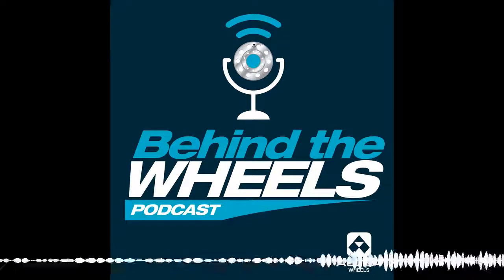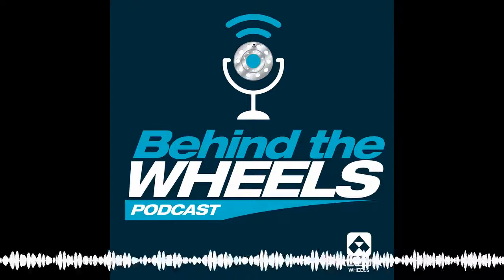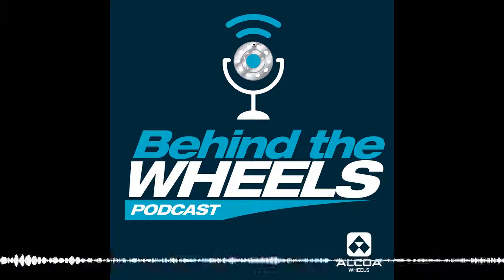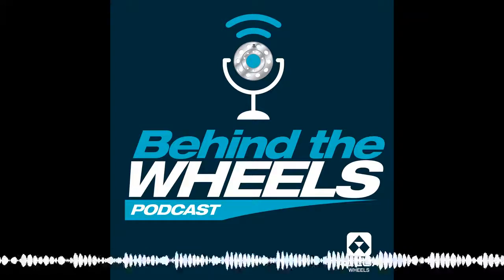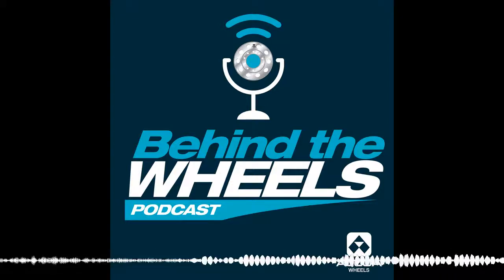Let's talk a little bit about the different coatings out there on the aluminum wheels. Let me jump on that real quick, Mike, because one of the most important things about the aluminum alloys used is that it's a heat-treatable alloy. We talked about this on a previous podcast, and those interested in more detail can go back and look at that. But you can take these wheels to too high a temperature and lose strength. That's obviously very important to know, and it becomes a major concern if you overbake them.